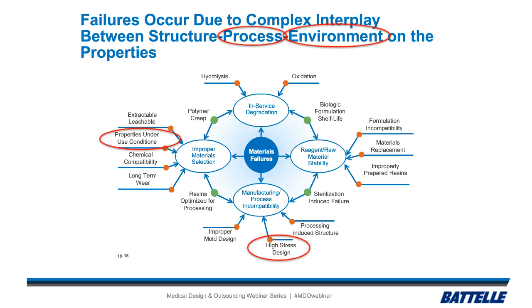So the properties under use conditions, which was, again, an ultra-cold freezer here, it was still above the Tg of the polymer, so the polymer was chosen correctly. This is not an issue of choosing the right material, but that was done properly. But what wasn't taken into account was the amount that the elongation decreased when we went from room temperature down to this very cold freezer. And the second part was the high stress design, so the stress in the corner of that material.